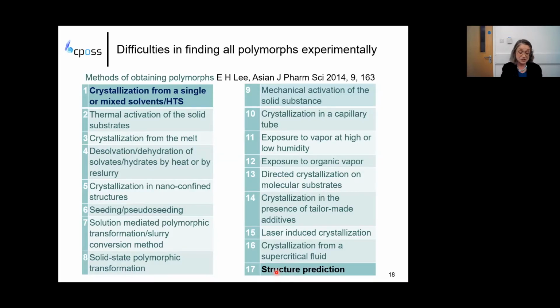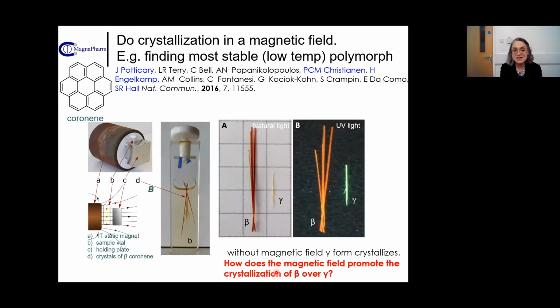Anyway, the past 5 years that have just finished have been funded by yet another method. If you try crystallizing in a magnetic field. So Simon Hall in Bristol and colleagues found the first example of a new polymorph of coronene by crystallizing in a magnetic field. And there you are, it's called the beta form, because of the packing. And they found this at room temperature. And on the basis of that, and the belief it was the more stable form, we were able to persuade the EU to fund a project to look at the effect of magnetic fields on crystallizing pharmaceuticals.